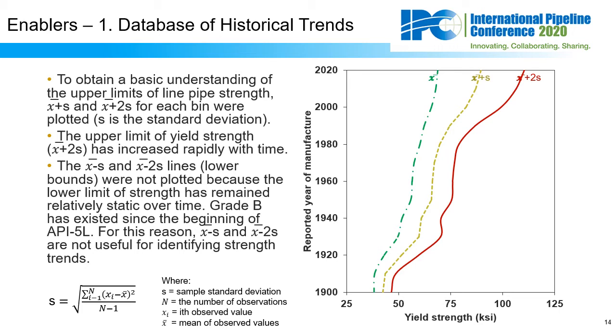So we didn't think it made too much sense to add a lower limit to the distributions for the yield strength plot, because grade B has been relatively static since the beginning of API 5L. So the lower bound could be assumed to be a straight line at low strength.